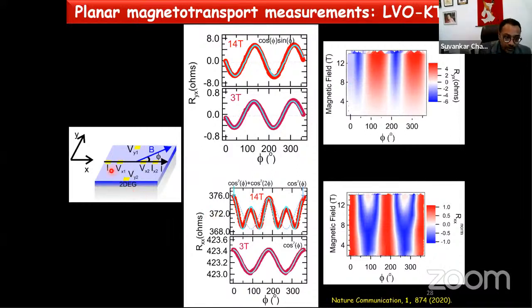But when we look into the longitudinal resistance, that is the anisotropic magnetoresistance, you can see at low magnetic field, you have a twofold oscillation which can be fitted by cos squared phi dependence. But at high magnetic field, an additional peak appears and it can be fitted only by cos squared phi plus cos squared 2 phi dependence. And this is the corresponding contour plot. And you can see that around 8 or 9 Tesla, starting from 2-fold symmetry, it goes to a 4-fold symmetry.